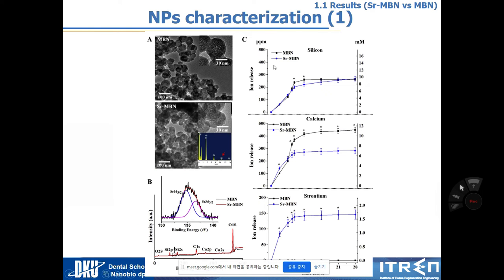So after making the nanoparticle, I want to look at the size as I designed. This normal bioactive glass nanoparticle is around 50 nanometers, as observed by TEM, a kind of microscope. When I add the strontium element, they also have a similar nanoparticle size of around 50 nanometers. And then I check the strontium element by XPS, another tool to check your element of interest in your nanoparticle. And then I want to check, as I designed, whether silicon, calcium and strontium can be released from our nanoparticle. The normal MBN without strontium only releases silicon and calcium ions.